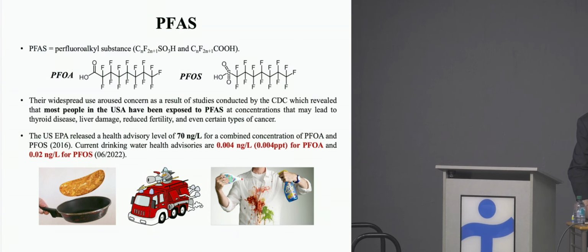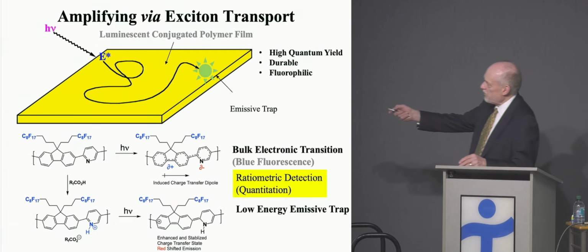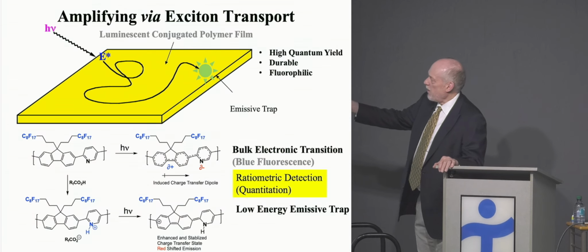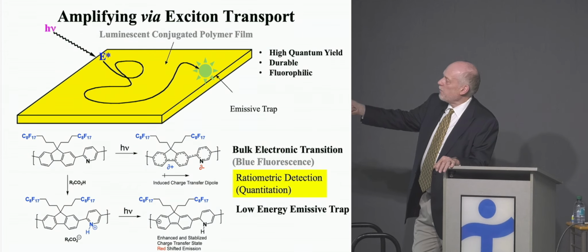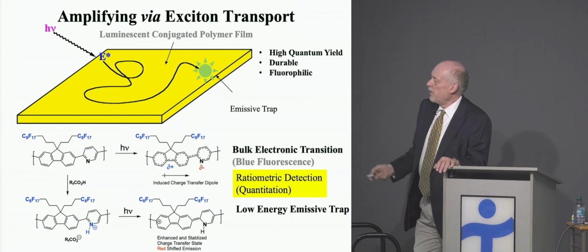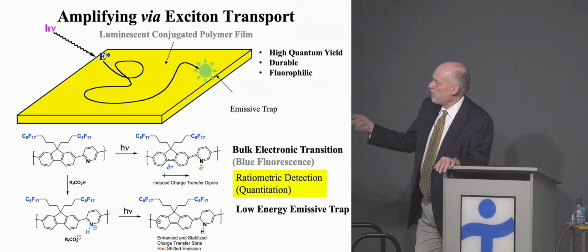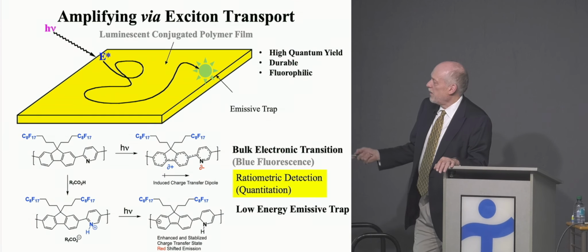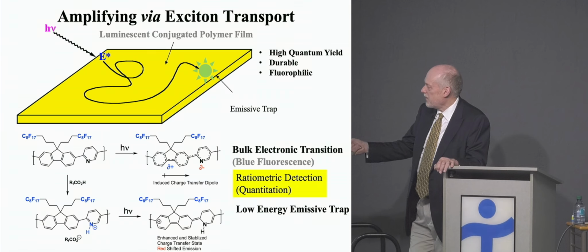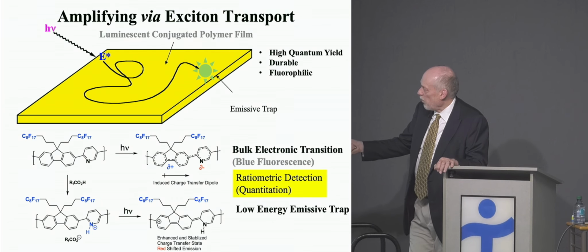Okay, so how do we take this scheme that I showed you before, and rather than kind of a black hole, I'm going to make it have a new emission here. So what we did is we made polymers that we put into these thin films, and this polymer has this nitrogen here, this pyridine. This is electron poor and this electron rich. So when you excite this with light, it tends to transfer electrons from this side to that side. It makes a dipole here.